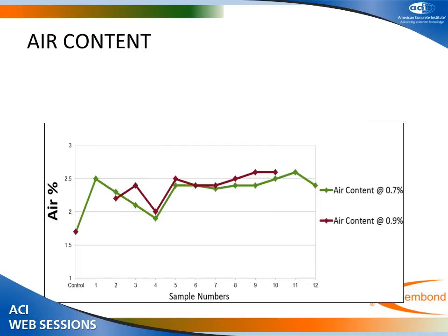This is the air content. Again, as I said before, because of the low water cement ratio and low dosages, the air content also remains stable. We have of course used a defoamer that I have not shown in the formulation. There was about 0.2% EOPO based defoamer used, and even for the SNF based, we used the same defoamer.